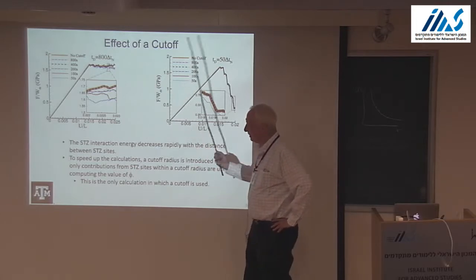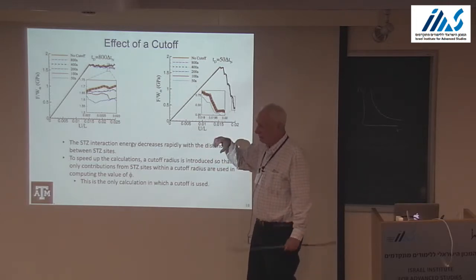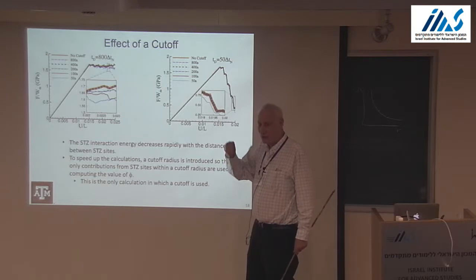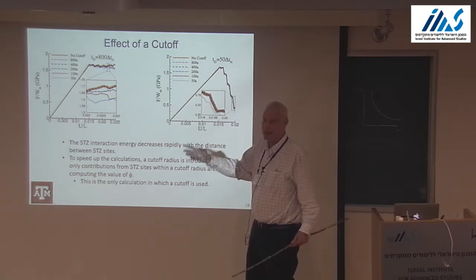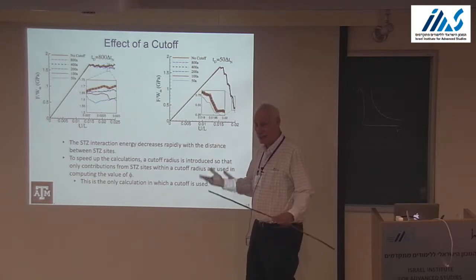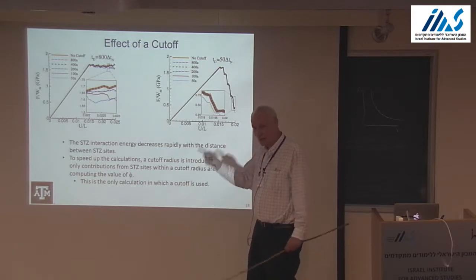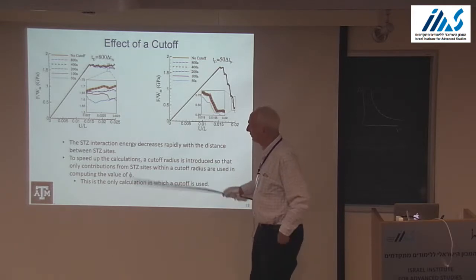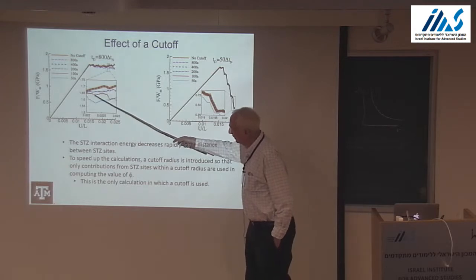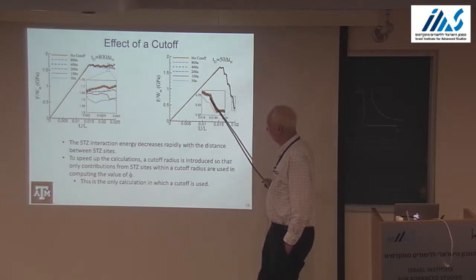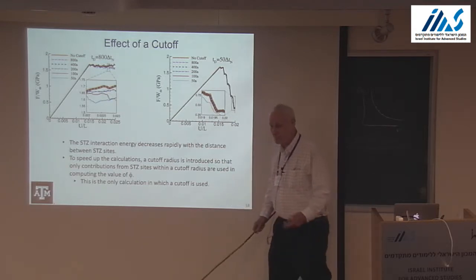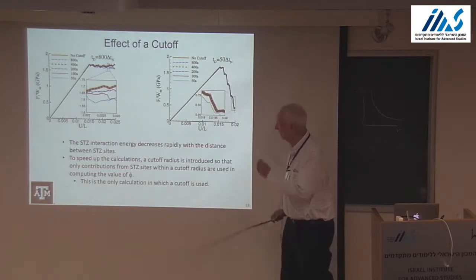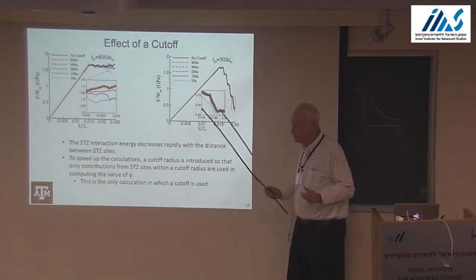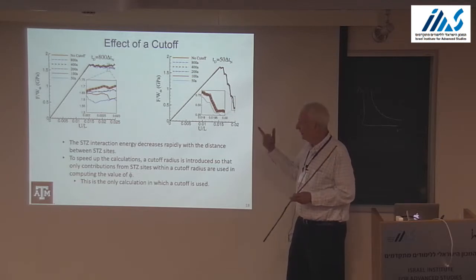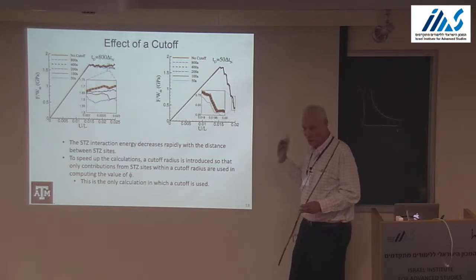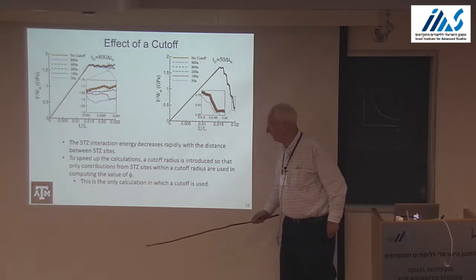One thing that's nice is that the elastic energy in 2D goes down as the fourth power, and in 3D even as the sixth power. So like in atomistics, unlike dislocations, we can actually use a cutoff to speed up the computation. Once the cutoff is large enough, everything falls on top. So we know what sort of cutoff, and it's actually several hundred times the STZ radius. So we have to be a little bit careful there.